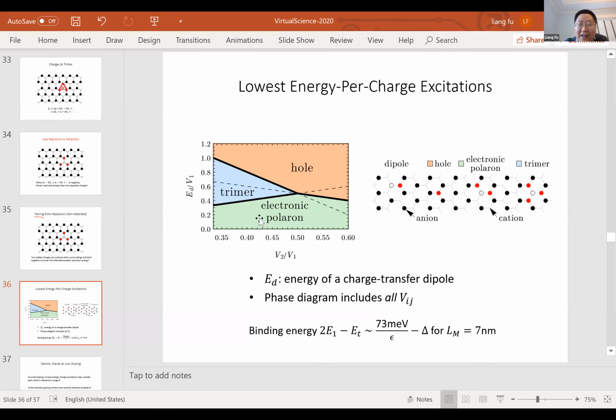So we can do the counting more carefully, to include all interactions, not just first neighbor, second neighbor. So when all the interactions are included, this is a phase diagram. It can be organized in this simple way. The x-axis is the ratio of the second neighbor repulsion and the first neighbor repulsion. The vertical axis, ED, is the energy cost of creating a charge transfer dipole.